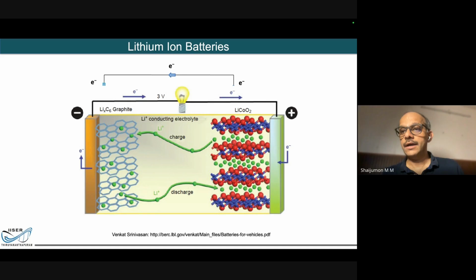So the very basic working principle in a lithium-ion battery goes something like this. When you buy a lithium-ion battery, these days it comes fully charged. In a completely discharged state, what I have is just graphite on the anode, and here it's fully packed lithium cobalt oxide. When I say fully packed, these little green spheres that you see are intercalated, or lie between these two layers of cobalt oxide. These are the cobalt oxide layers, and these green ones are the lithium, sort of sandwiched between the two layers. So that's the lithium cobalt oxide.